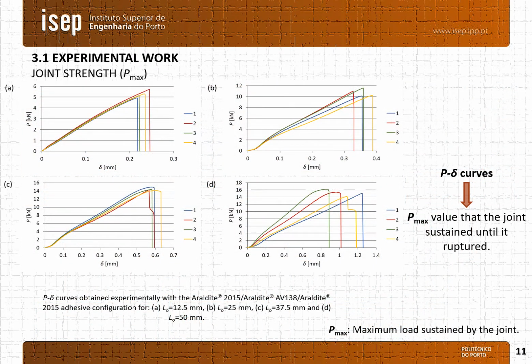Here are shown the experimental results for the dual adhesive configuration. Graphic A is for an overlap length of 12.5, B for 25, C for 37.5, and D for 50 mm. Overall, the results are very consistent with the exception of the overlap length equal to 50 mm. Here, the Pmax values are in good agreement, but the displacement at failure exhibits some differences, probably due to some slipping in the testing machine.